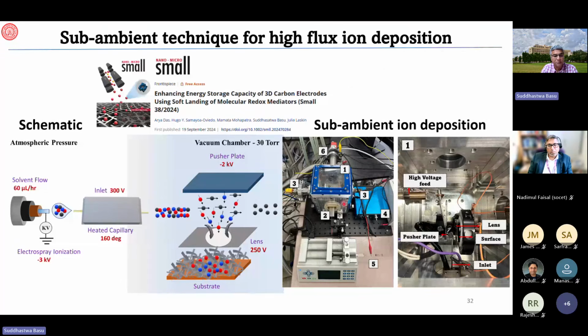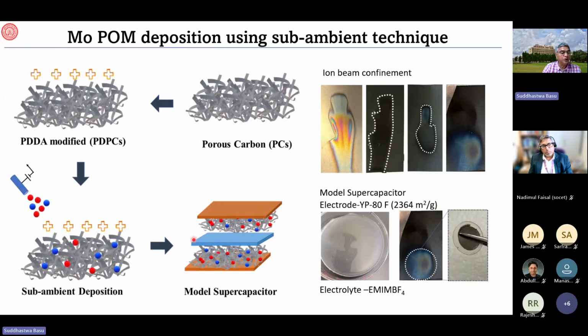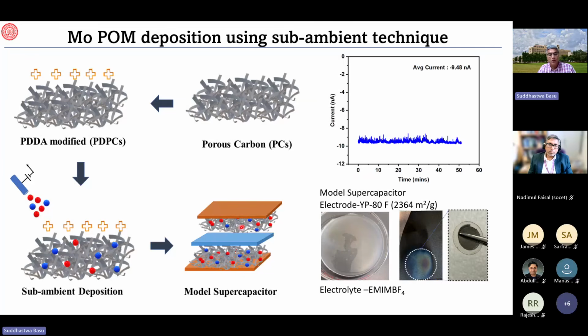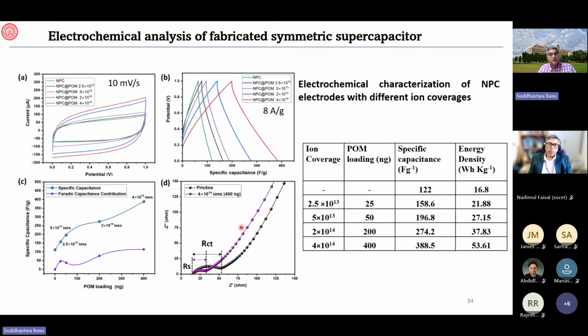This is an ion implantation chamber. As I said, because we call this a lens, when we spray that in an electrospray ionization chamber, we have these ions, cations and anions. Then both go through this slightly heated zone, activated through a charge difference, and only one of them passes through. We did it for the cations, and anions are left behind, and then we deposited it as we are showing you here. And because of that, we got a very good supercapacitor performance as shown here.